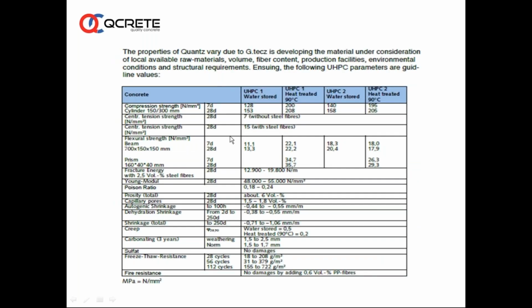Another example where normal curing, the strength is 128, 153. So here we should not compare with the strengths that we get by cubes. It is cylindrical strengths actually. So if you convert this to cube strength, it is higher actually.